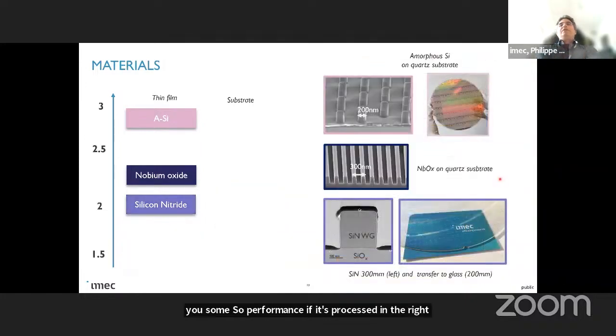We have been processing these different kinds of structures, so with silicon nitride on glass substrates. These are structures that are either directly processed on the glass or layer transferred onto a glass. We do the work for niobium oxide and amorphous silicon. Here you can see some examples of 200 millimeter wafers that have this flat optics type of structure.